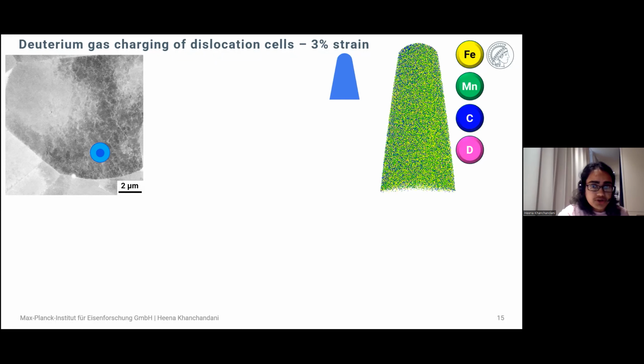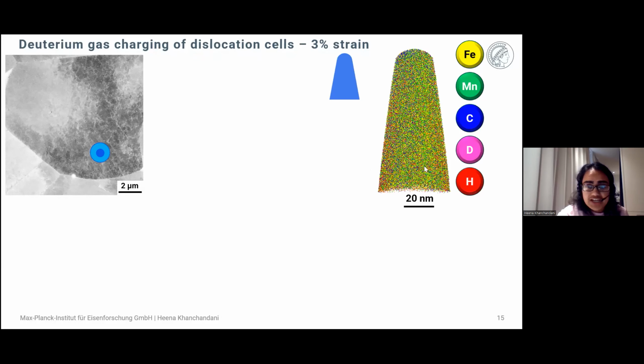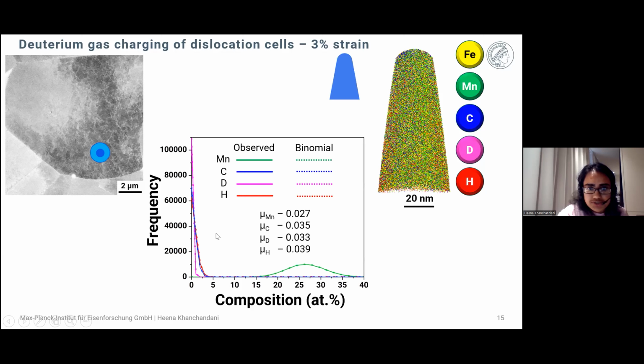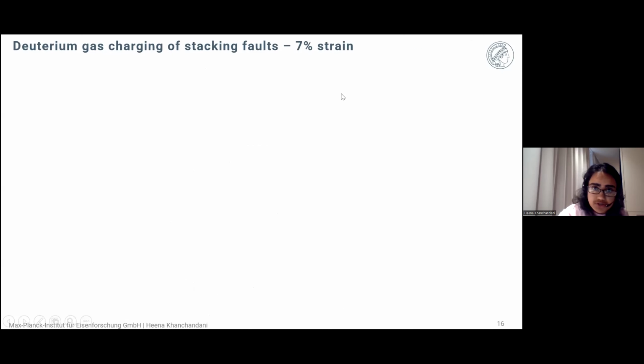For this, we also mapped the hydrogen distribution in the sample, and hydrogen was also not segregated at any specific features. So we also plotted the frequency distribution analysis, which shows that there was no segregation of deuterium or hydrogen at any specific feature or at any dislocation. Similarly, we performed this analysis on the sample with stacking faults, which were formed at 7% strain.